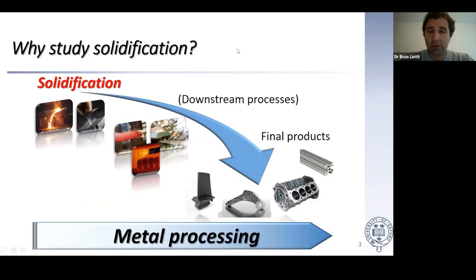Solidification science underpins many of the critical sectors in the metal industry, and in particular, if we look at the metal processing chain, solidification is the first step. In fact, pretty much any metal component has gone through the liquid to solid transformation at some point, either by casting or gas atomization. Therefore, the microstructures that are developed during the solidification steps have a very strong influence on the final product properties. And the reason why we study solidification is to learn how to manipulate this microstructure to be as good as possible in the first step.